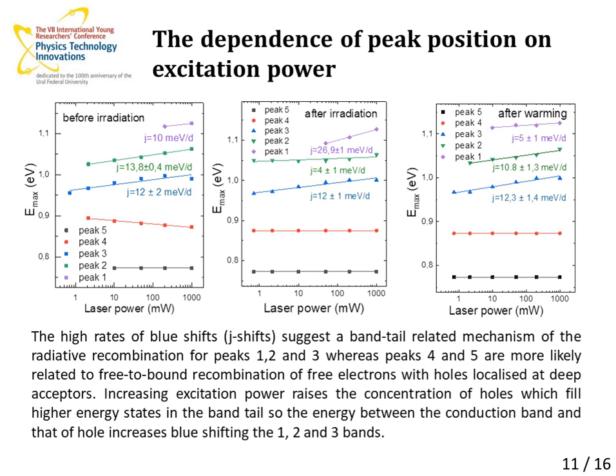In our case, 3 main bands shift to higher energy with rising excitation intensity. The high rates of such blue shifts suggest a band-tail mechanism of the radiative recombination for the 3 main peaks, whereas the 4th and the 5th peaks are more likely related to the free-to-bound recombination of free electrons with holes localized at deep acceptors.